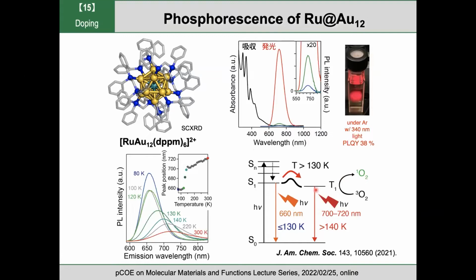But when we reduce the temperature of the system, the luminescence peak is gradually shifted, and below 120 Kelvin, the peak is suddenly blue shifted. And we assign this intense band as fluorescence from the singlet states. So depending on the temperature, the origin of the luminescence changes between phosphorescence and fluorescence. But I want to emphasize that the quantum yield is very high by just adding a single foreign atom at the center. So the doping effect is significant in the photoluminescence property.